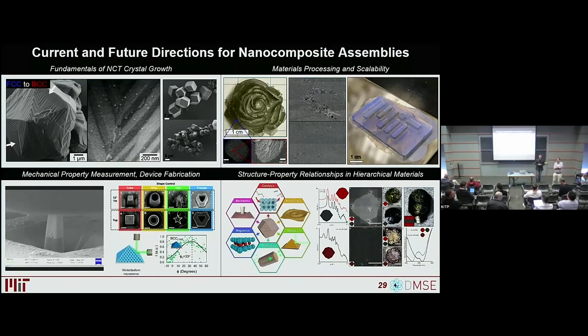I was wondering if you could give us a sense of the freedom you have in designing some of these systems in terms of the particle size and maybe the polymer length and maybe the density of those polymers on the surface of those particles. Yeah, so we typically work in the 10 to 50 nanometer range just for simplicity, but we've assembled them as large as, I think the largest we've gone up to is about 80, and we can do larger, say 250, 300 nanometer sized particles. They don't crystallize quite as well, and we think that's because we just have not had time to look into the thermodynamics and kinetics of that.